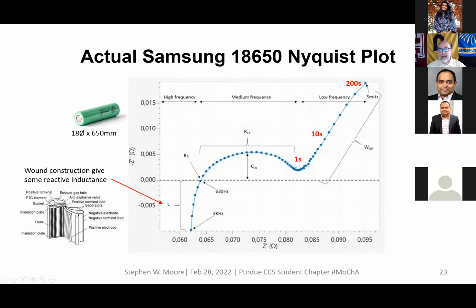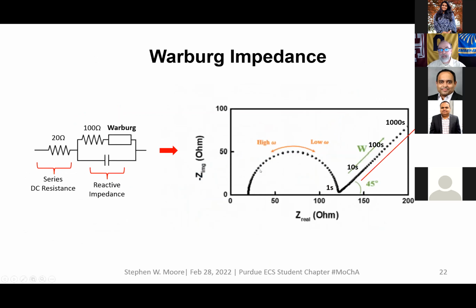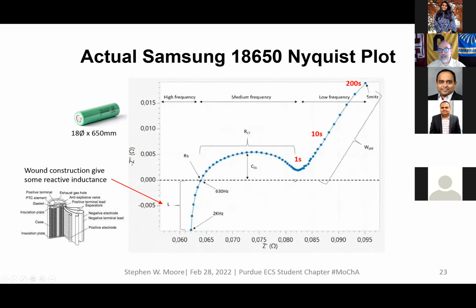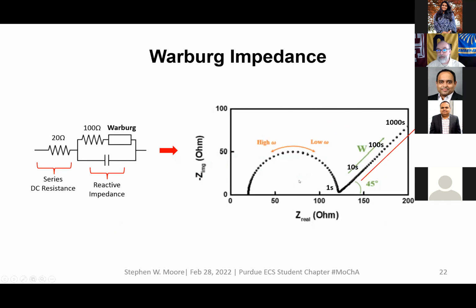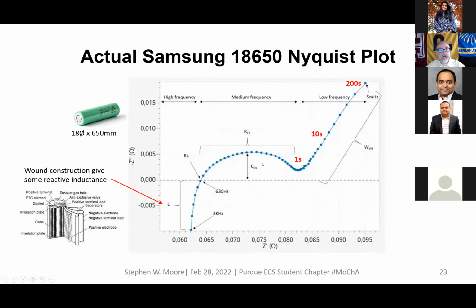So you can see that this Nyquist plot is really, really similar to the one I can model. So this is a really good model, actually, for modeling terminal voltage. It's pretty close. I think it works. And it does work in real life. The problem is a Warburg impedance is impossible to convert into discrete time space. So if you're doing anything that requires data sampling, you can't do calculations for the Warburg impedance. It doesn't work because the differential equation cannot be converted using a Z-transform into discrete time space. So that gives a little bit of a problem of how to model this Warburg tail. So that's where it gets complicated.